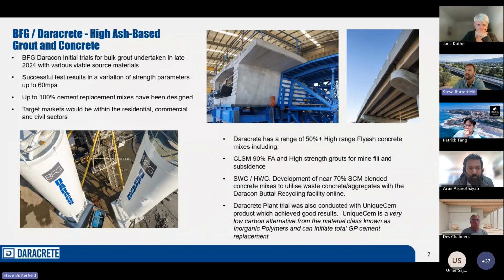And BFG Group also had initial trials for bulk grout undertaken in late 2024 with various source materials again. They've had successful test results in a variation of strength parameters up to 60 MPa. They've had success with up to 100% cement replacement mixes being designed. Obviously, the target markets would be within the residential, commercial, and civil sectors.